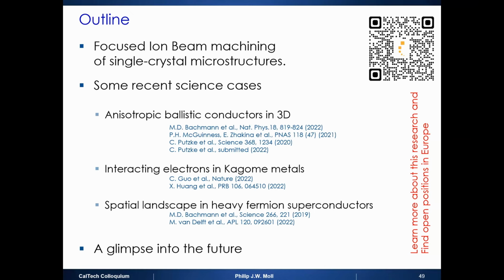Tellurides and selenides are really hard to work with. The uranium telluride almost took a year to get the right recipes going. The cesium vanadium antimony is easy to make, but to get it strain-free was a big hassle. So getting all of this membrane-mounted technology up. So it's very difficult to say. After a year, we tend to give up. So there's some things we had to give up.